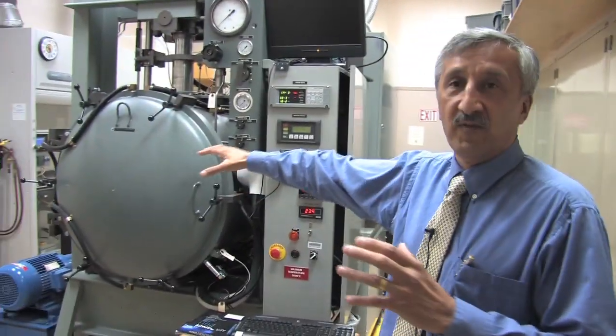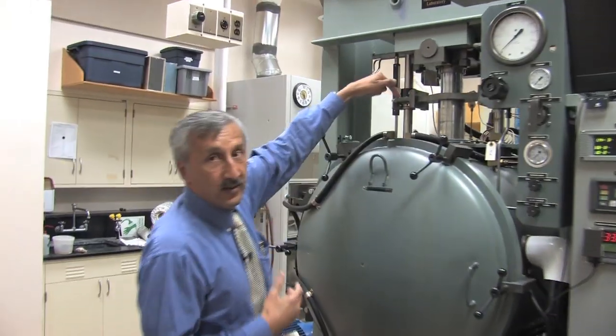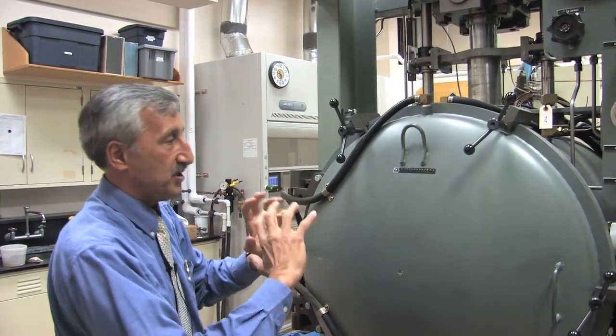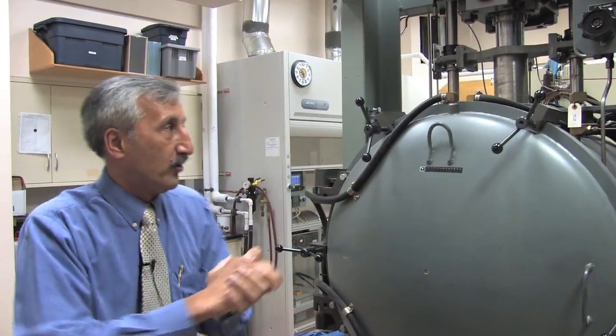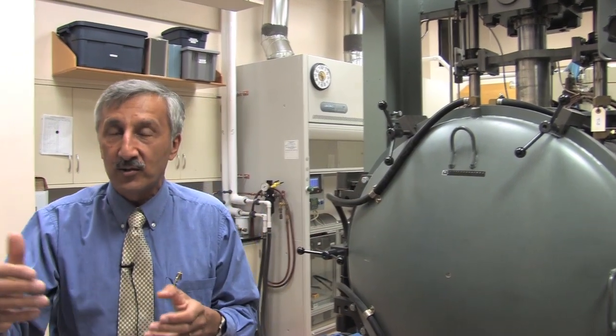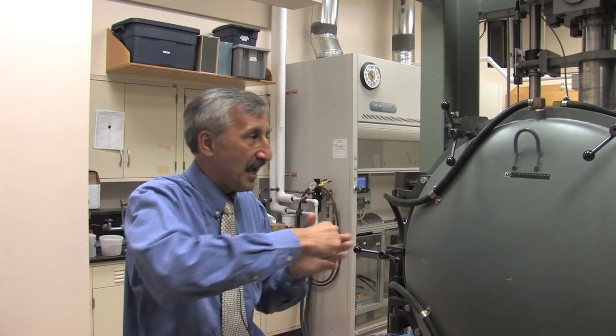This machine is basically a vacuum furnace. Inside there you'll see a piston coming down this way, and there's one up here — these pistons basically squeeze down. Inside I've got a mold, my powder is inside the mold, and we evacuate to get the gas out, then raise the temperature to about two thirds of the melting temperature. So I'm not going to trap any porosity — my powder is coated so it will uniformly densify. By controlling the shape of the ends of the pistons I can control what comes out, whether it be a flat window or a conformal optic, all done within a few hours.